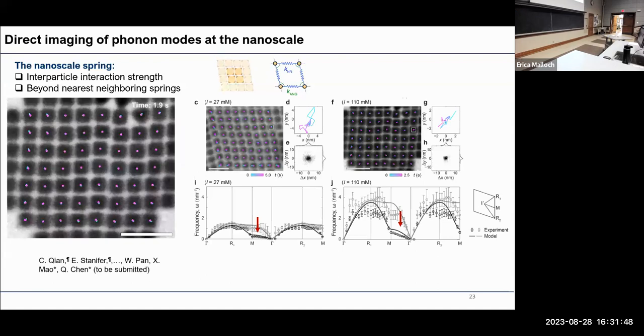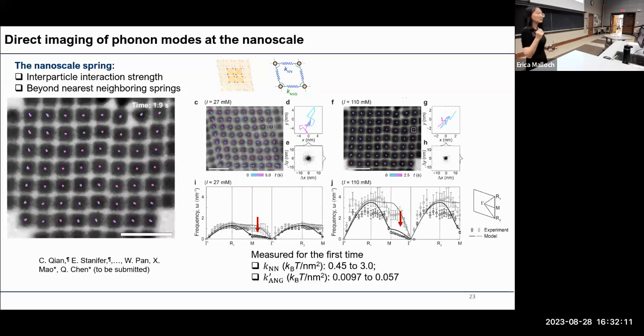And second, as I mentioned, fundamentally, the soft modes are determined by springs. So Xiaomi was able to develop a theory to model both the nearest neighboring spring, which is K_radial, and the K angular, which considers the next nearest neighboring effect. So together, using this model, she was able to fit our experimental data really nicely, so we can measure the nanoscale spring constants in the system.